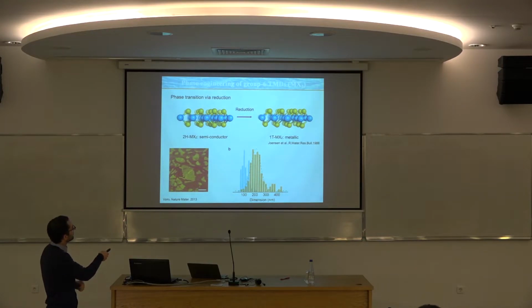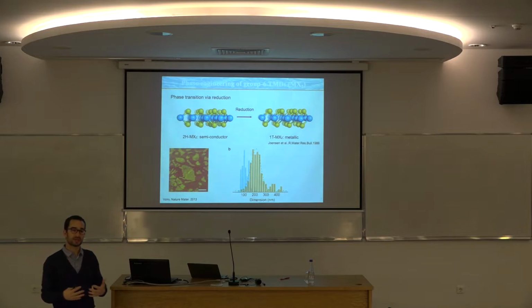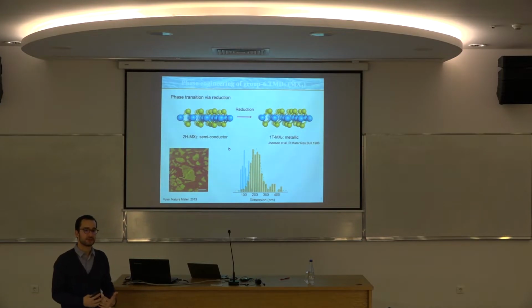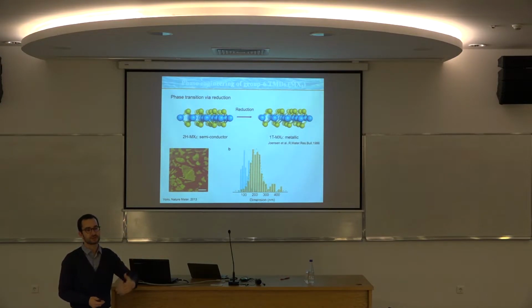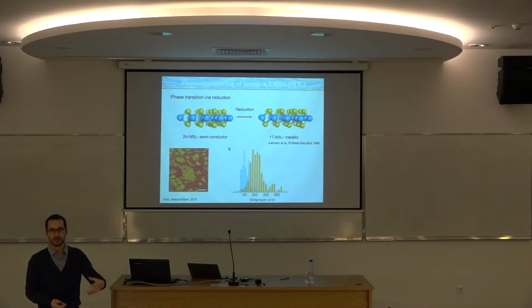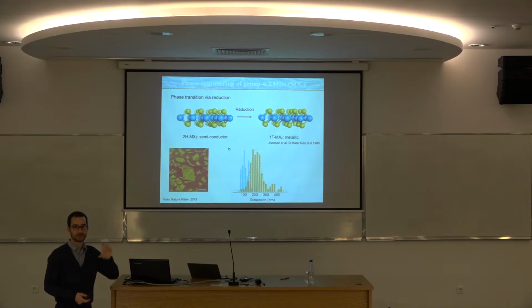and at the end, you have intercalated this bulk powder. You can exfoliate in water, do some centrifugation steps. You can purify away the non-exfoliated material, and at the end, you will have a solution of 100%, or close to 100%, single layer nanosheets in solution. Doesn't mean that the reaction is 100% efficient, but it's very easy to separate bilayer, trilayer, and bulk or aggregates from the single layer. So at the end, you have a solution in water, which is also quite easy to work with, of single layer nanosheets with this 1T phase.